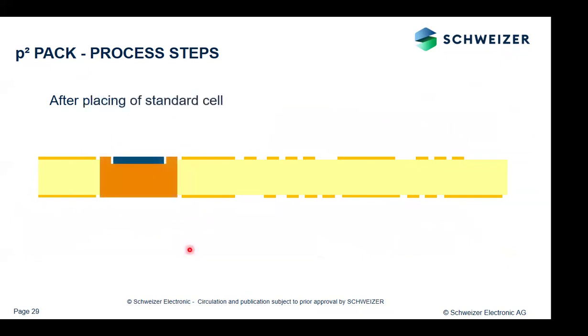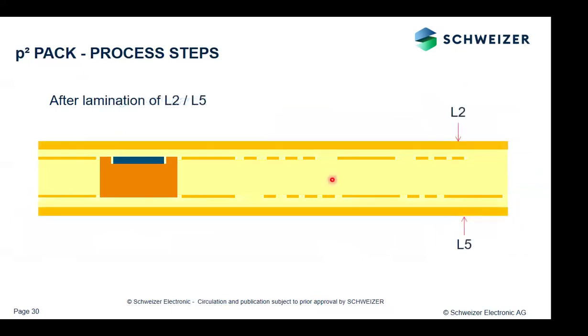And in this opening, we are placing our standard cell. So the standard cell and the inner layer, they are adapted from the thicknesses, so they fit together perfectly. So for the material that we're using here, we have a limited tolerance for the thickness, because this is important for the whole process. When you go to the lamination process, you are typically using so-called pre-preg layers at the top and at the bottom of this construction, and you add copper foils at the top and at the bottom.